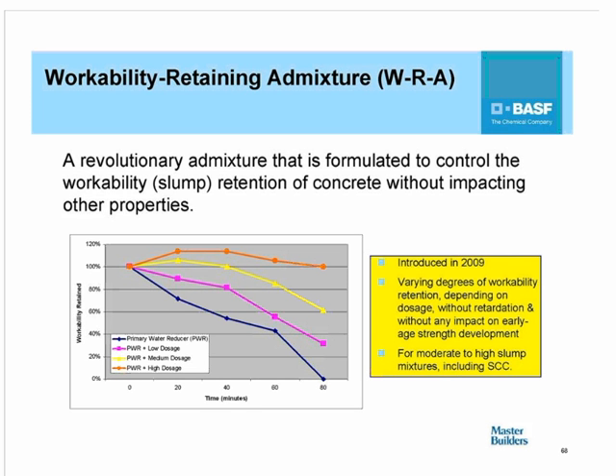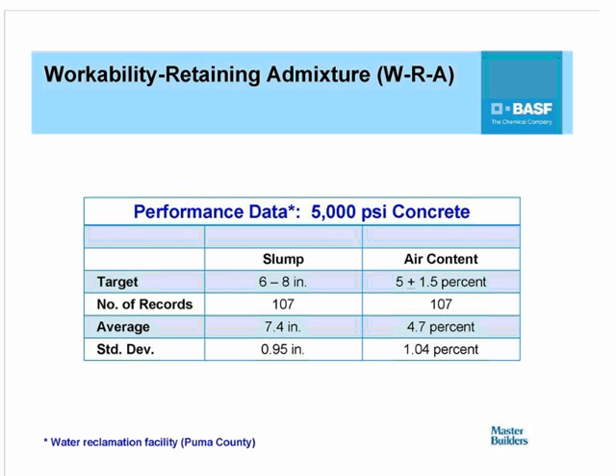And the main benefit of the workability retaining admixture is that unlike a retarding admixture, it does not retard the time of set of the concrete, and as a result of that, it does not impact early age strength development. It's primarily used in moderate to high slump concretes, including self-consolidating concrete, but it's also been used in lower slump concrete mixes. And here's just some performance data that I'd like to share with you.